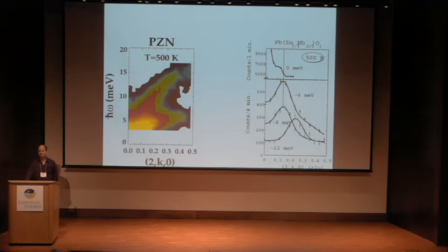Yeah, but the Bragg condition is different. If you're at a certain point in Q, all that matters in that case is just the angle of the crystal with respect to a fixed incident wave vector. In one case you have fixed EI, and in the other you have fixed EF and you're varying EI, so you end up with it in a different place, and it has a different locus in Q space. Sure. So the bottom line is I haven't looked at your time of flight data in detail, no.